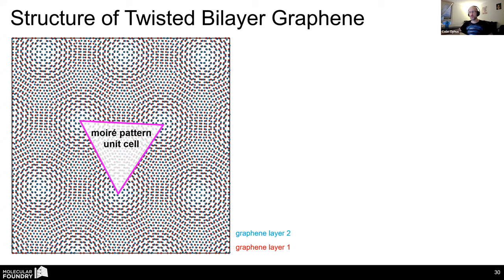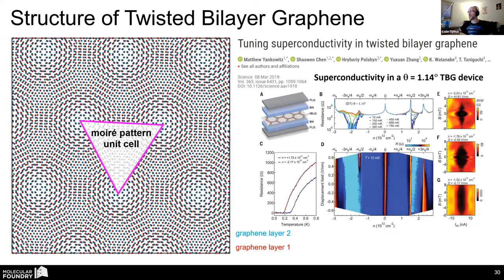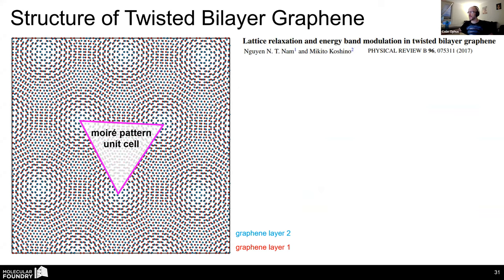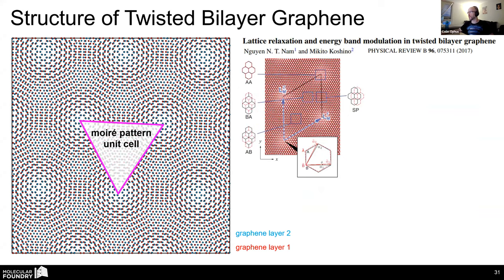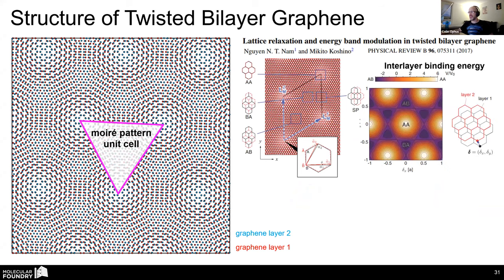And these sort of twisted bilayer materials have a whole host of interesting electronic properties. I'll just mention one, the sort of very famous magic angle superconductivity paper here. And a ton of work followed this up to sort of model these in simulation. And one of the predictions that came out of a lot of the modeling and simulation papers is that the AA stacking, of course, where carbon atoms are directly on top of other carbon atoms, is very unfavorable. AB stacking, where you have a one-third unit cell shift, that's the graphite structure, it's very favorable.